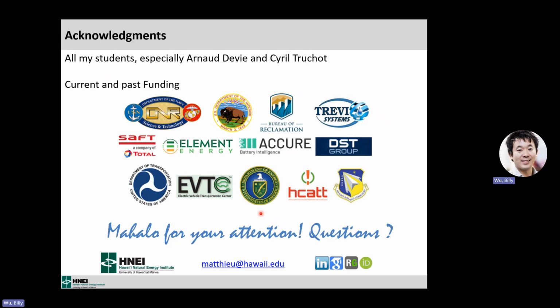The last question, to broadly stay on time. Ignoring silicon, graphite is probably the most dominant anode material. Yep. But even within graphite, you've got natural graphite and synthetic graphite, and they often blend them together. Do you see much variation in natural versus synthetic, or can we just take a graphite OCV curve and say that's it, we're done? We never look at that in super detail, but we notice that depending on the manufacturer, sometimes the graphites are quite different. We see it in the length of all the plateaus, and we see a lot of variations there.